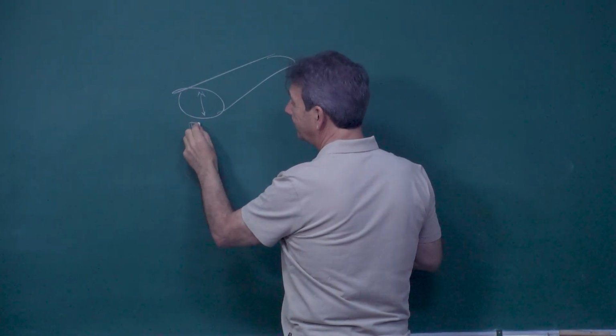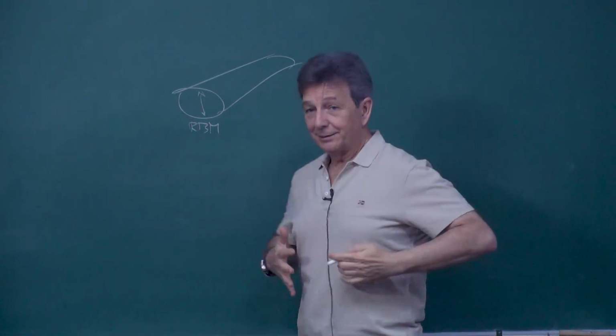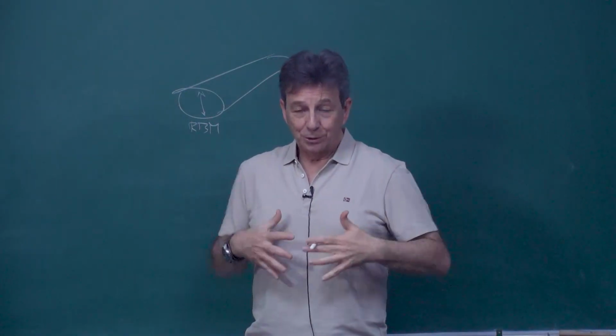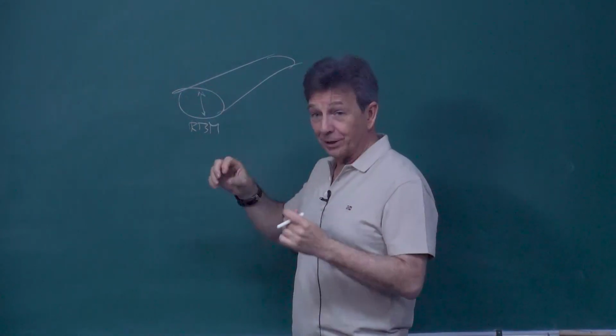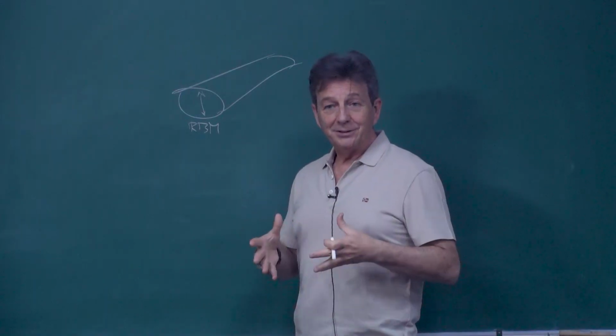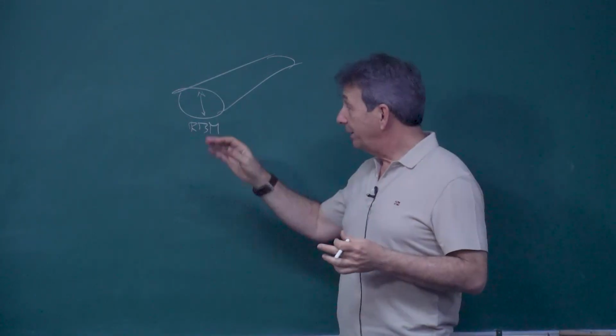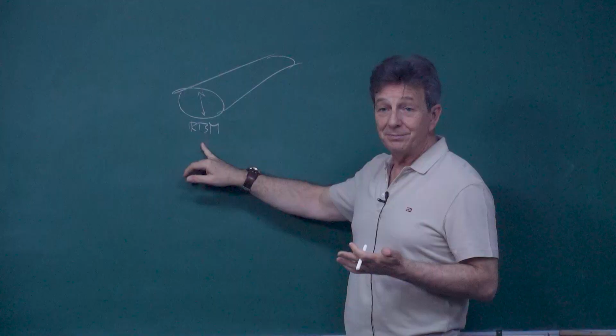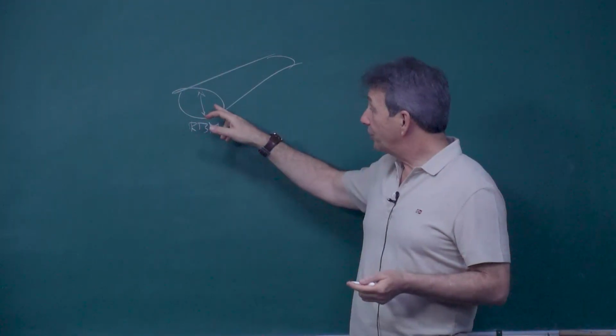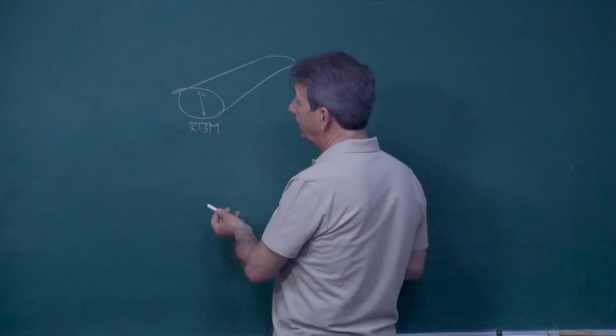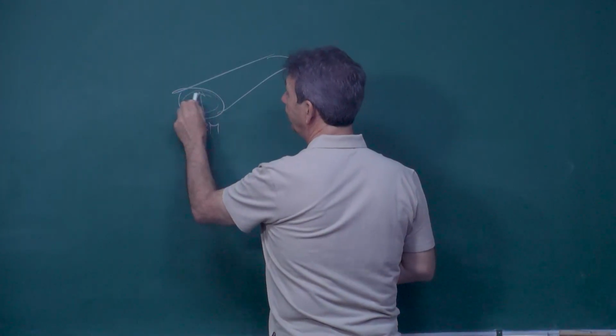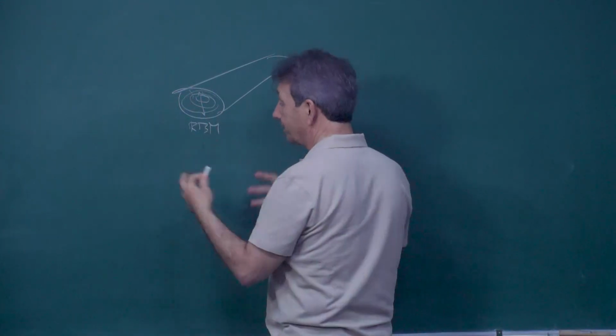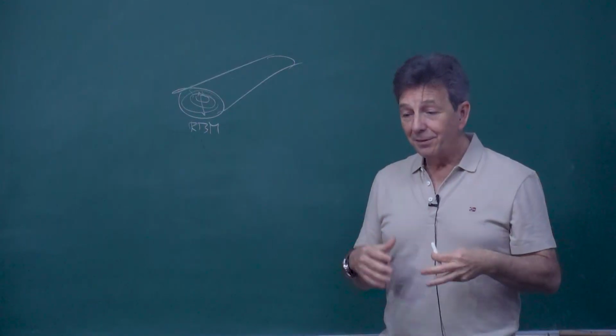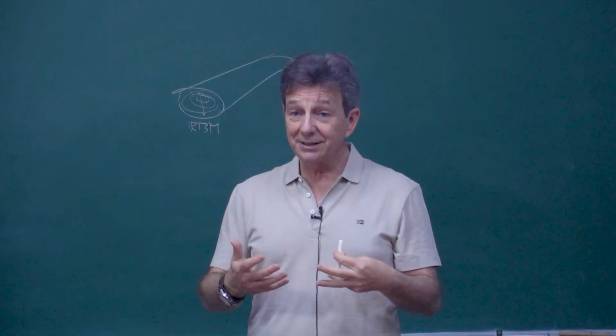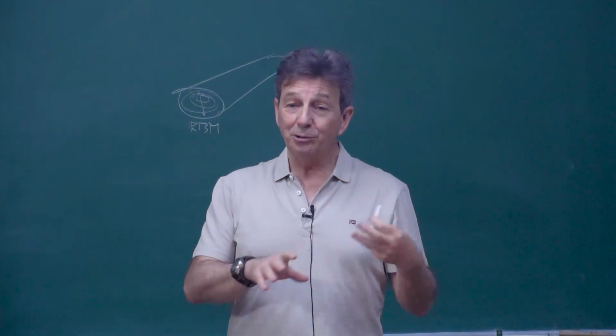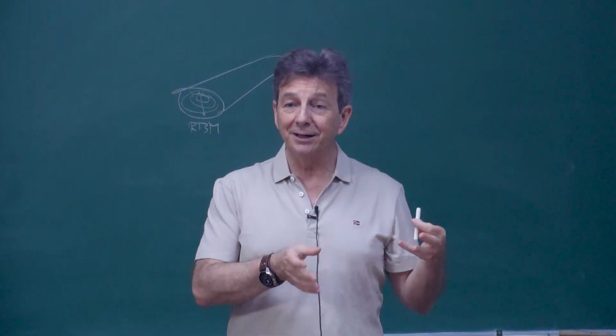So this nanotube will have a lot of vibrations, and one of them is the radial breathing mode. It's like your chest. So it's like it goes bigger and smaller on the vibration. It's like breathing. So this is the radial breathing mode. With near infrared, it's very well described, very well commented, because it won't be the same for a single layer nanotube as for a multi-layer nanotube, where you have multiple layers, because that will be affected. These kinds of things, for instance, are very well described with near infrared, but if you are using green or violet, you hardly find any literature.